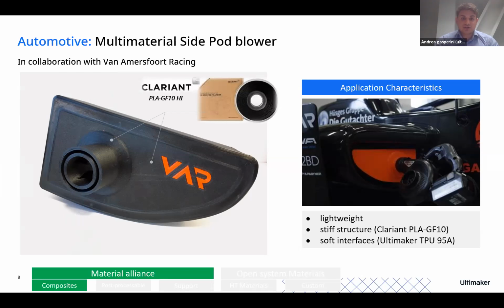The stiff internal structure that you can see in the middle is produced with the Clariant PLA-GF10 composite material, to impart stiffness and rigidity, and also to have a lightweight structure compared to metal sheet. The outer part instead has to fit within the car, so as not to scratch it. We have a really good cushion effect, and it seals very well in order not to have any air blowing outside of the part. It was produced with our Ultimaker TPU 95A.